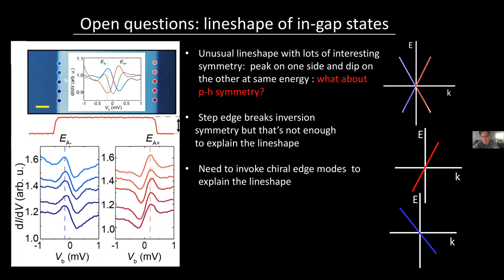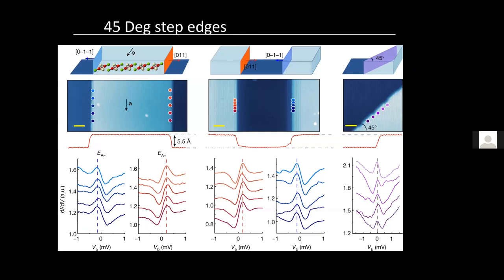What this basically means is that the right step edge is not equivalent to the left step edge for the superconductor in the superconducting state. In order to explain this, I think you need one more ingredient — either two boundary states interfering, or some process where tunneling electrons are doing something giving a certain line shape. If you had a 1D mode spanning the superconducting gap, you'd expect a flat density of states inside the gap on either side of the Fermi energy. If you add those together you get a flat density of states — but we're apparently only seeing half the spectrum, and I don't understand why.